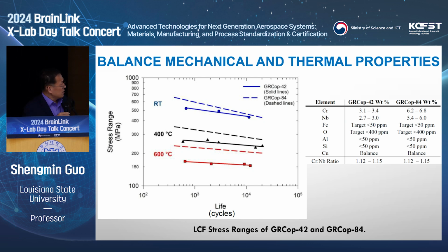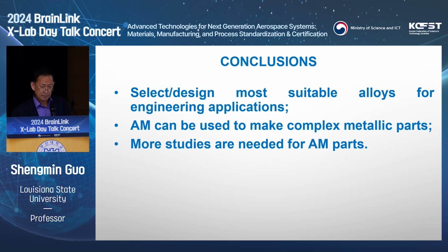At 600, you see the value for the solid line, which is GR-COP 42, gives you a mechanical strength over 150 megapascal. And I believe when you heat it up to 700, this 3D printed alloy, for rocket engine components, can still have a mechanical strength over 100 megapascal. Due to the selection of a material utilizing additive manufacturing technology, we can incorporate a very complex cooling design into your parts. So that's the message I want to pass by today. Well, somehow this video won't play. Okay, I guess we want to play.